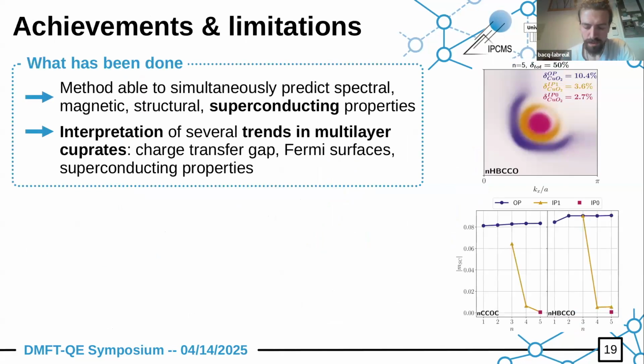So just to quickly remind what has been done in this work, basically we set up a method that is able to simultaneously predict spectral, magnetic, structural, and superconducting properties from the same framework. And from that, we could provide some interpretation of several trends in multilayer cuprates regarding the normal properties such as charge transfer gap, Fermi surfaces, and so on, and properties which are not obvious to predict in principle, which is this doping homogeneity. And then we can make the link with the superconducting properties and understand these trends of superconducting properties in these multilayer cuprates.